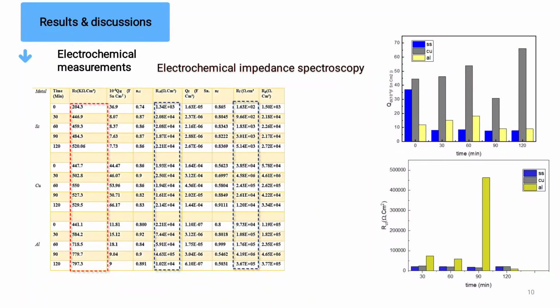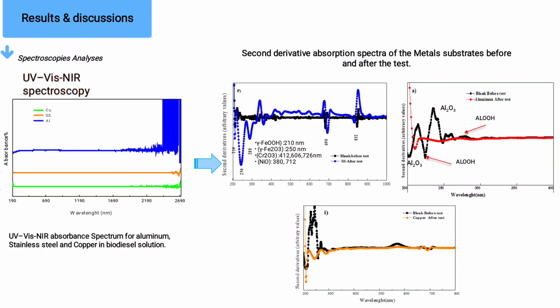As we can see, the aluminium exhibits a higher Rf resistance to corrosion, which means high protection. The ultraviolet-visible spectroscopy exhibits a higher corrosion and metal loss due to biodegradation for the copper surface. The stainless steel in biodiesel showed intensified oxide peaks, iron and chromium, indicating a strong protective film, possibly from biodiesel breakdown products. The aluminium's initially protective oxide layer was weakened by biodiesel, but then reformed, suggesting improved corrosion resistance in the long run.